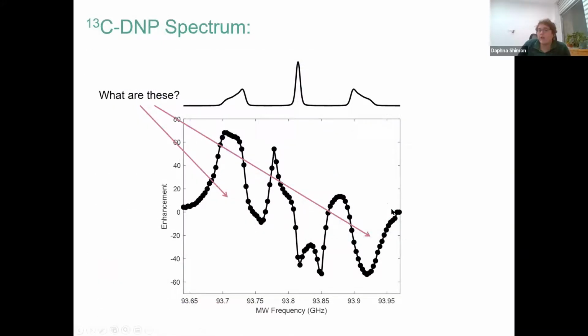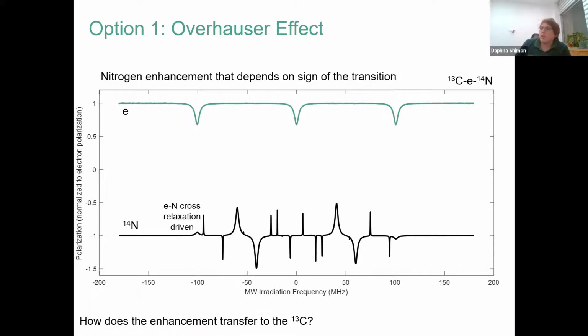So back to the big question, which is what is it that we're seeing on these peaks here? I'll go back to the Overhauser effect for a second, and I'll tell you that I did some simulations looking at an electron coupled to a nitrogen and a carbon. Here, if we look at the nitrogen, you can see that there are enhancement peaks on the nitrogen at the exact frequency of the two outer EPR lines, and they have opposite signs. So this looks exactly like what we see in carbon.